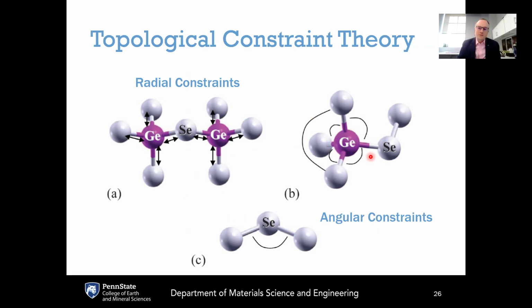This was originally proposed by Jim Phillips back in 1979, and he did it initially in the context of chalcogenide glasses, specifically looking at germanium selenide systems, where what he did was to count up the number of rigid bond constraints in the glass, where if you've got, say, a tetrahedron around germanium, you count the number of rigid bonds here around the germanium. You also count the number of rigid angles that can occur around the germanium or around the selenium. And if you add up the total number of these rigid constraints, so add up all the rigid radial constraints and all the rigid angular constraints, Phillips proposed that the optimal glass formation should occur where that total number of rigid constraints is equal to the total number of the atomic degrees of freedom.